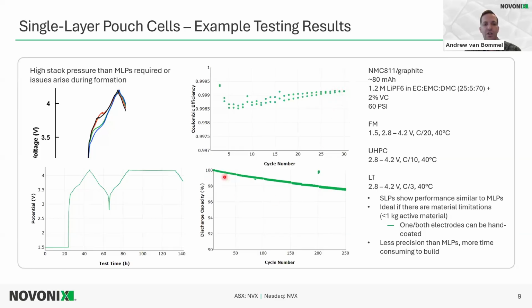If we look at long-term cycling data, so these cells afterwards were put on long-term. That's why you don't see the normal larger decay at the start of long-term and then the flattening out. So you just see a flat discharge capacity versus cycle number. So this was C/3 cycling at 40 degrees, and we're approaching 98% capacity retention at 250 cycles at C/3. So this performance is similar to multi-layer pouch cells.